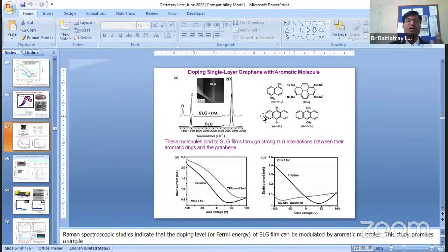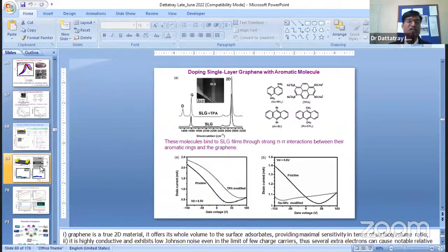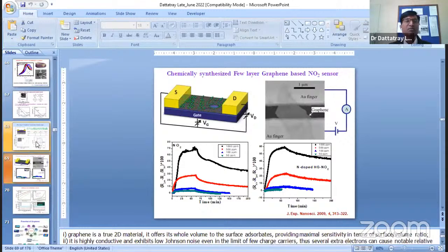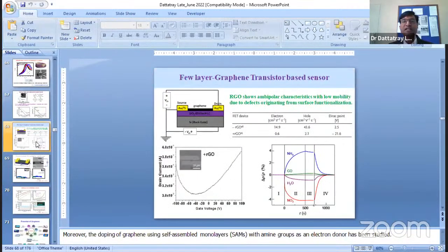Maybe a shifting, or, now this is single layer graphene Raman spectroscopy. The moment you have something on the surface, now there is some defect induced on the surface of graphene, right? So it immediately shows the D peak, right? So that is also a kind of signal we can use to understand and measure some of the other properties of graphene. Of course, one of the properties of graphene is as a sensor.